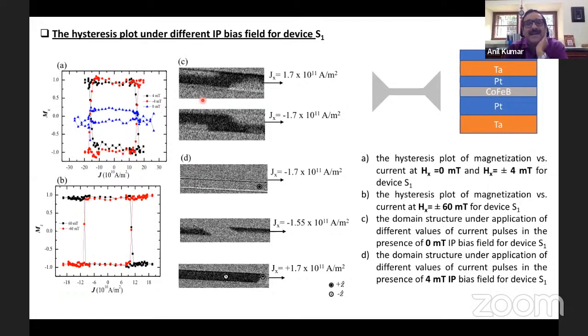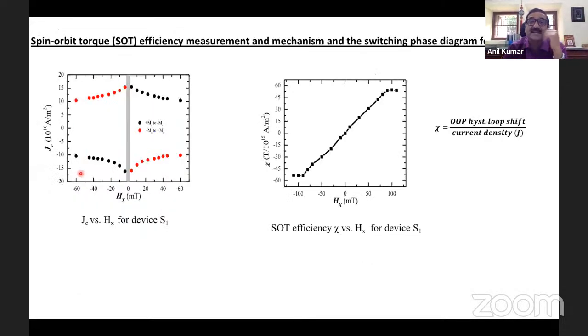Now if I remove this in-plane magnetic field, you see that the magnetization reversal is not complete. So that means in the absence of a magnetic field, I'm not getting the magnetization reversal in this kind of structure. If I apply more magnetic field, like a 60 millitesla in-plane field, the critical current density is well defined here. Now I can generate a phase diagram, which is called a switching phase diagram, where I plot the in-plane applied magnetic field against the critical current density. You see that when I apply zero magnetic field, I don't get a magnetization reversal. So here also, I need to apply an in-plane magnetic field to get magnetization reversal, but I'm getting this at 1 times 10 to the power 11 ampere per meter square.